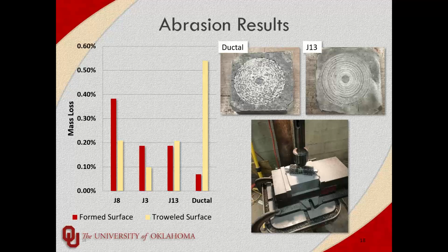And we didn't seem to have that in our mixes for whatever reason, which is why it appears that our trowel surfaces perform so much better than Ductal. But that's mainly because we didn't grind the top surface. We just tried to keep it apples to apples. But if we were to grind the top surface, you would have the same level of performance with the Ductal and the trowel surface as you did on the form surface, which would make sense.